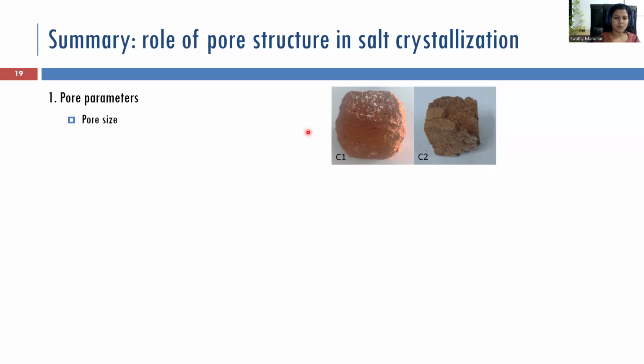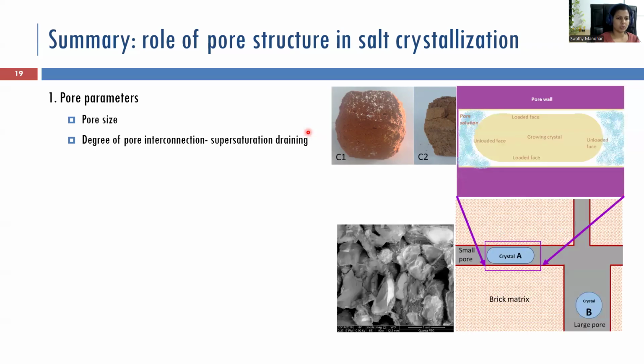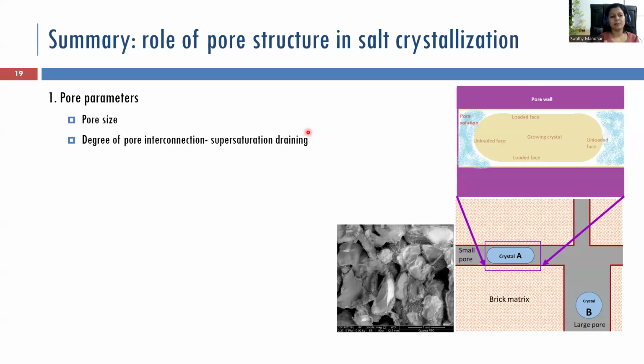Larger pore samples always behave better with salt crystallization because salt can grow in all directions in a larger pore - it will not cause crystallization pressure. But in a smaller pore, it will cause crystallization pressure and damage the pore walls. Coming to the second parameter, which is the degree of interconnection.